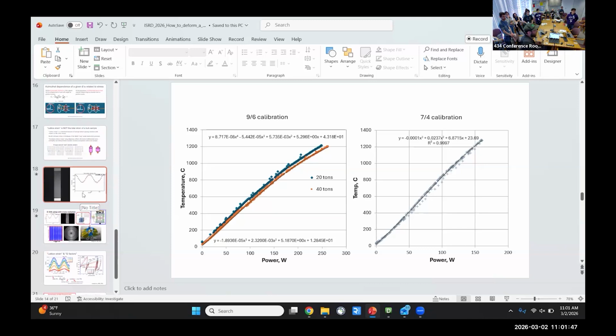Is there a correction factor to account for the difference? I mean, you could come up with one. Typically, if we run a calibration experiment, although this isn't all the time, if you had 25 tons, you could try and come up with some correction factor between these two. Usually, if I'm at 25 tons, I'll just use the one for 20. I should also mention that there's uncertainty with this setup. So your temperature could be off by 25 degrees easily. Under sort of weird strain situations, it might even be off by 100.